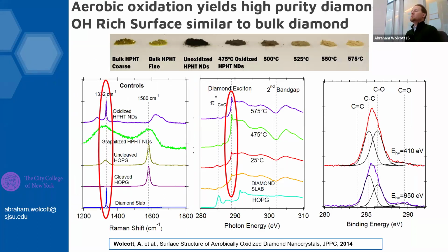So this material looks like this as we get it from the manufacturer. This is the bulk version. This is after ball milling. And then we can go ahead and remove the amorphous carbon and purify the material using Raman spectroscopy, X-ray absorption spectroscopy in the middle, and XPS. We concluded many years ago that the HPHT material, though it's on the nanoscale, is basically just like a single crystal diamond.